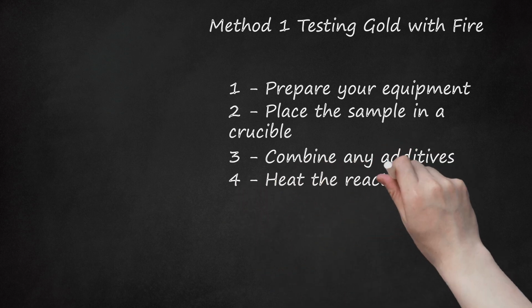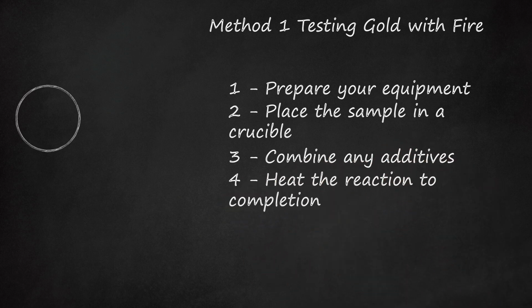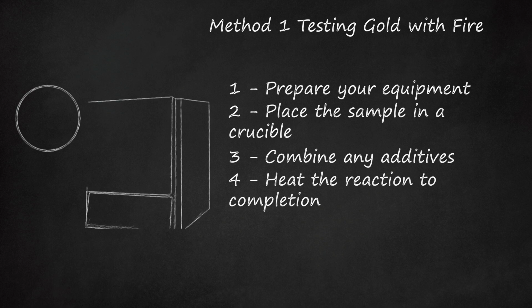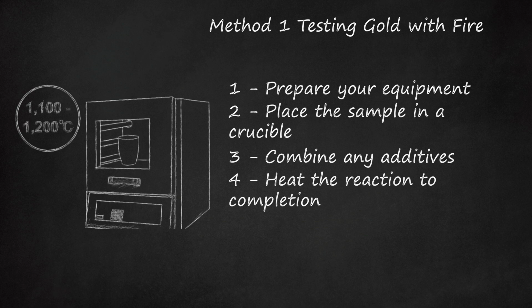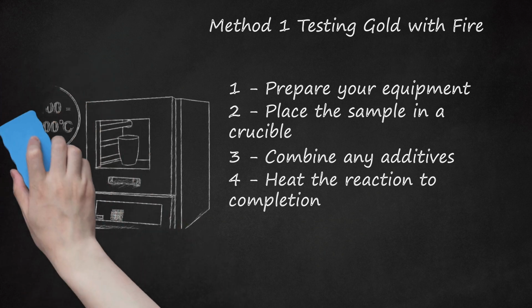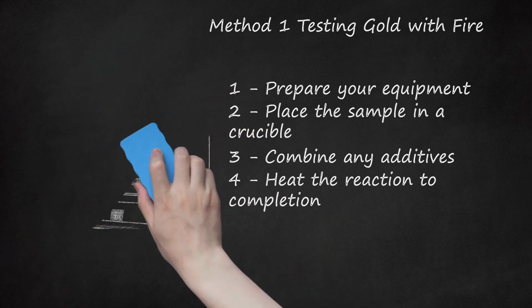4. Heat the reaction to completion. The flux reaction needs to be heated to completion. When the reaction is complete, you will see two separate layers. Depending on the laboratory and the additives used, you will typically heat to between 1100 and 1200 degrees Celsius, 2012 to 2192 degrees Fahrenheit. The top layer is molten glass that contains no valuable minerals. The bottom layer contains your molten precious metals.